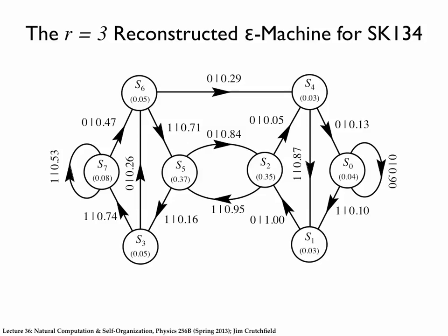In order to get from the 2H crystal to the 3C crystal, it follows a path like this. It doesn't just do anything to get there. It actually has to follow a particular path. Of course, it could do something like this, and there's a missing transition here that we could have had, but we do not. And it could do this and then go around, but this is the most likely route. So we can calculate the probabilities, and when it looks like it's breaking the usual periodic structure, we now know how that break occurs and what it looks like. It's not just an arbitrary thing. And we can assign probabilities for each kind of path to get to something over here.